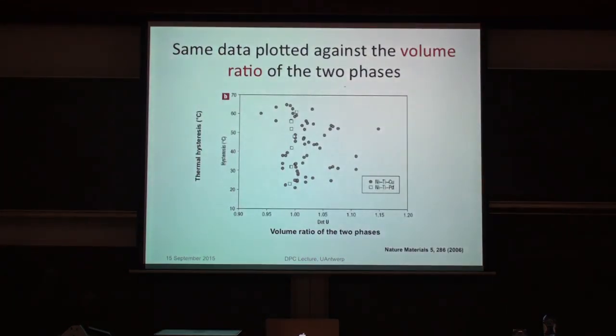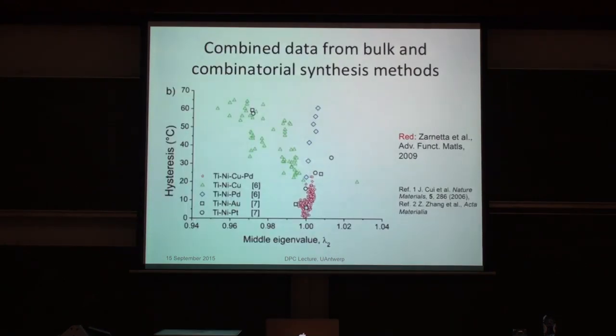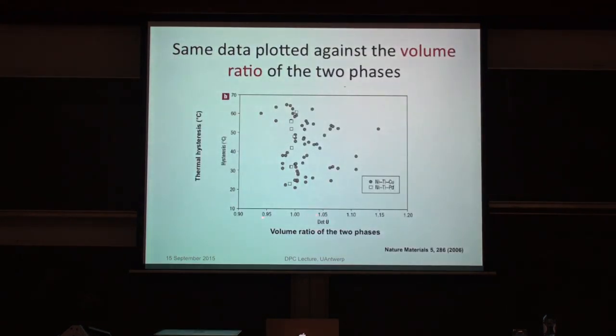Okay, so here's an interesting graph. Now there's a way to make materials with very low hysteresis, and I'll tell you a bit more about some of those materials. This is a graph. Now I've replotted it, and in all those alloys we knew all three of the eigenvalues, and that allows us to calculate the determinant of this matrix U, this transformation stretch matrix, which is the volume ratio of the phases. So if there's anything that should affect the hysteresis or produce an energy barrier, it's if the new phase is growing in the wrong volume, right? A volume which was too big or too small to fit it, right? That's exactly what happens if this determinant U is not 1.